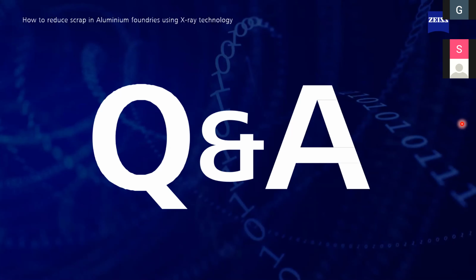So I can take the name of one company, Mahle, for piston manufacturing. They have been using this 2D technology and also magnetic particle inspection, and they were rejecting their parts. Their rejection was almost 8%. And after using the X-ray machine, they identified that of all the 8% of scrap which they were rejecting, almost 5% of the parts which were rejected can be used without undergoing any further process. This is what they could realize, and the other customer